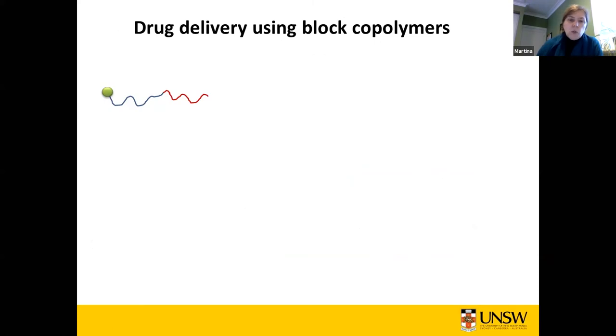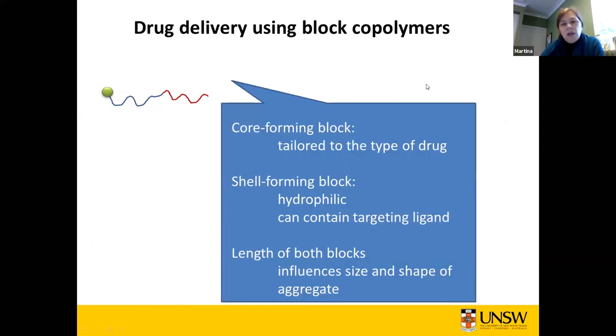So because we have now this tool set where we can make so many polymers in a very short period of time, we can always tailor our polymers to our drug delivery problem. So this is our polymer here, and now we can modify these polymers depending on what we want. For example, the red block here, that's the part that would be in contact with the drug you would like to deliver. The shell part here, the blue one, would form the micelle shell, and it needs to be hydrophilic. And this is basically what the body sees. So if your blue part is not functioning well, the whole nanoparticle is not working well. And you can, for example, have a little targeting ligand here. So the length of both blocks influences the micelle size.